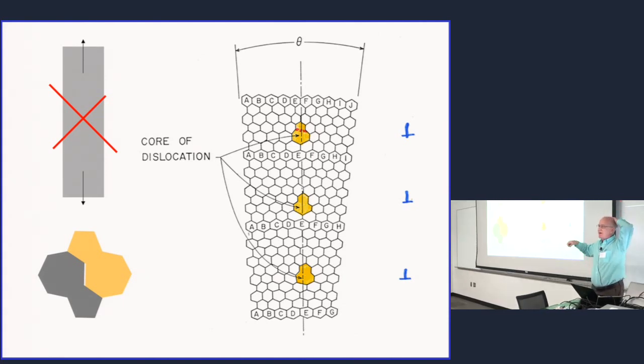And then you think, okay, so I should look at graphene, graphite, and you look at this paper. It's not even cited here. It's like 1956 or something, the Thomas and Roscoe paper, which shows a hand-drawn, of course, they didn't have computers, hand-drawn low-angle grain boundary in graphite, graphene. For us, it's graphene. For them, it was graphite. And you see, oh, very nice. This is a low-angle grain boundary, which means that these pear-shaped yellow objects must be dislocation cores. They are dislocation cores. These are symbols. Okay, this is a low-angle grain boundary.